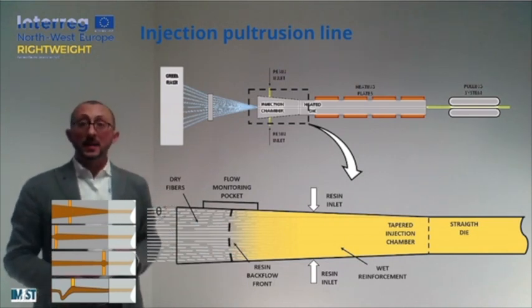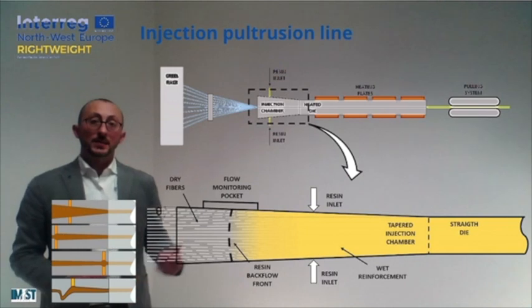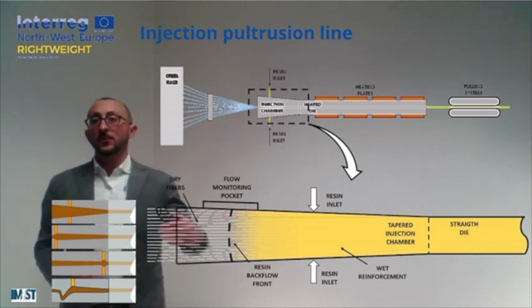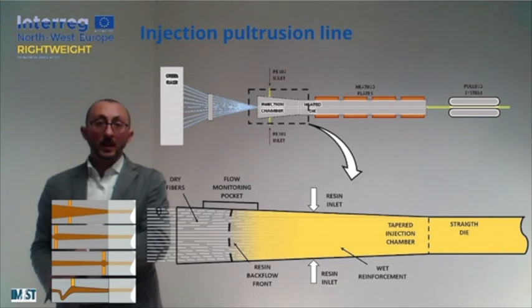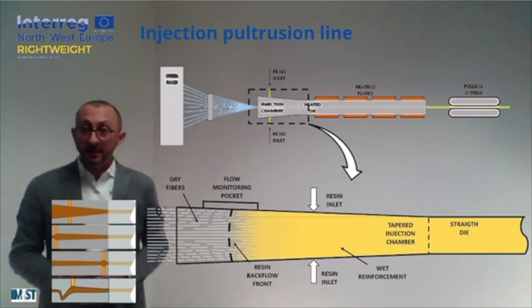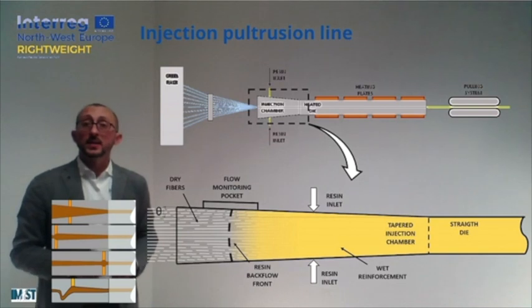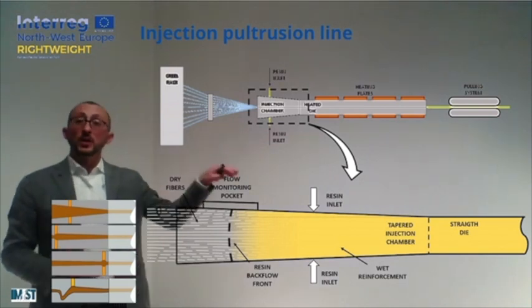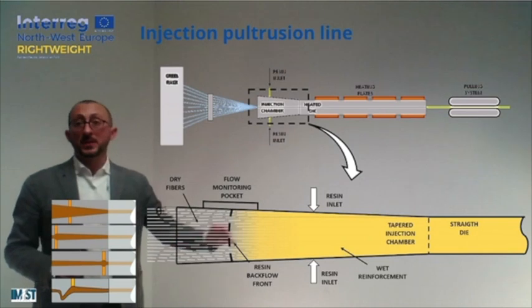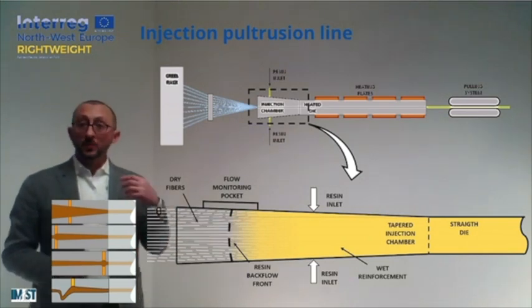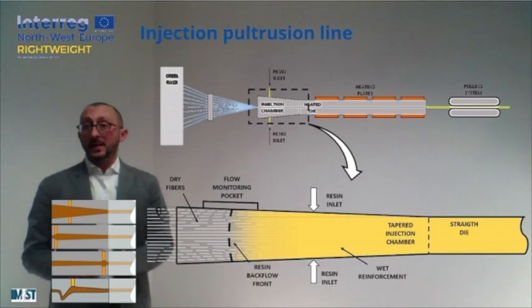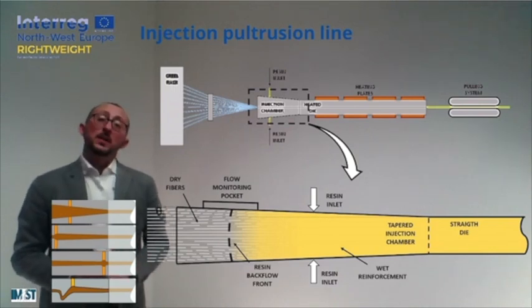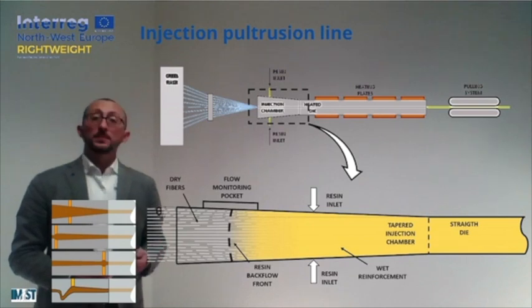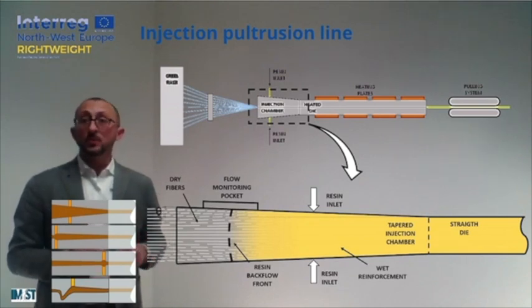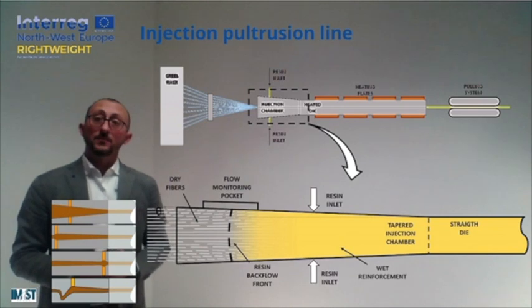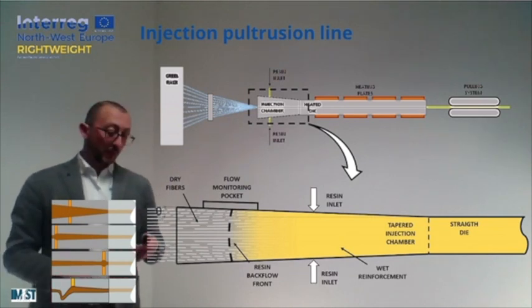But at the same time, what we should avoid is that the resin will flow back, flowing out at the beginning of the chamber itself. So everything here is just a game of injection pressure and pulling speed. And what we need in order to obtain a good balance, a good calibration of these parameters, is to combine them in order to completely wet our reinforcement without this kind of backflow.